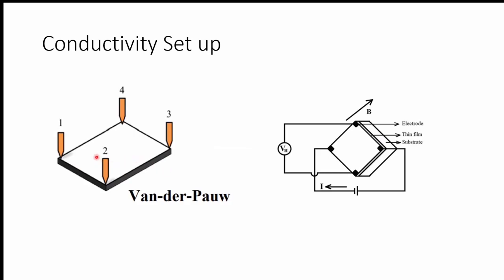Now, how do I measure this conductivity? Basically, we use the van der Pauw method. There are multiple methods to measure conductivity, but this is the one we use. We use gold contact pads to reduce contact resistance between your connections and the electrode and your polymer film. You have voltage on two electrodes and a current on two electrodes, and it's coupled to a computer that tells you the resistivity, and you plug it into the pre-programmed equation to give you a conductivity based on the thickness of your film.